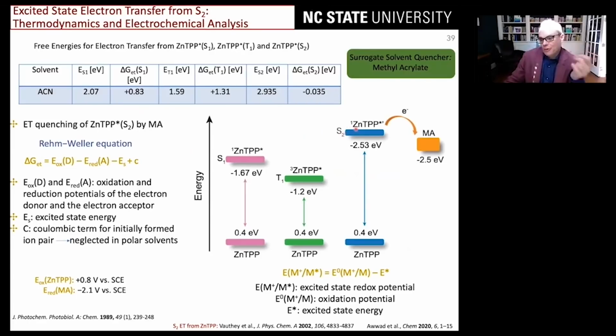But the S2 excited state, which is really Soret excitation, gives you a higher energy excited state. And this is the only one that's downhill to actually be quenched by electron transfer from these acrylates. We use methyl acrylate as a surrogate because it won't polymerize. If we use our typical cross-linked acrylate, this polymerizes right in the cuvette and it's very difficult to get spectroscopic measurements. It's a lot easier if what you start polymerizing is still soluble. That's the only reason we use methyl acrylate.